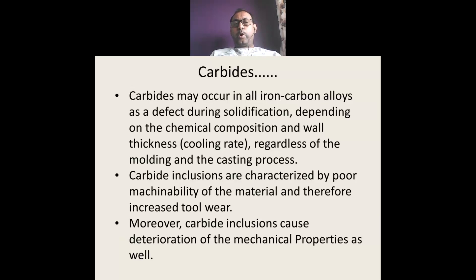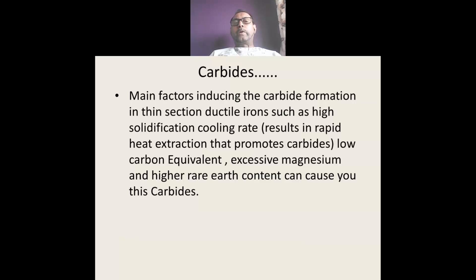Carbides. Carbide may occur in all iron-carbon alloys as a defect during solidification, depending on the chemical composition and wall thickness — that is, cooling rate — regardless of the molding and casting process. Carbide inclusions are characterized by poor machinability of the material and therefore increased wear on tools. Moreover, carbide inclusions cause deterioration of mechanical properties as well. Main factors promoting carbide formation in thin-sectioned ductile iron include high solidification cooling rate, which results in rapid heat extraction that promotes carbide.